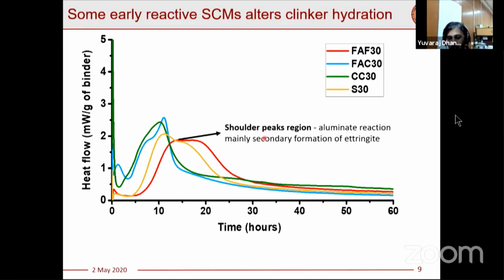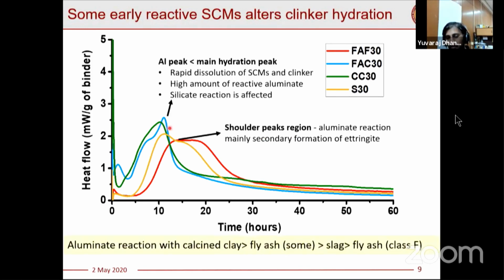So in these two cases, which will be the case in some SCMs, what happens is the aluminate reaction starts happening before the main hydration period. So when this happens, the silicate reaction is affected. So basically, you have rapid dissolution of these SCMs, and it also has a higher amount of reactive aluminates. So it shifts the curve quite rapidly.